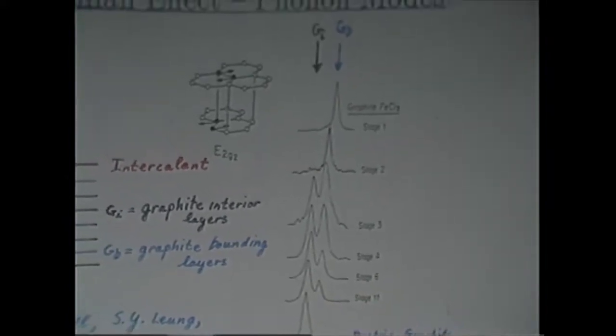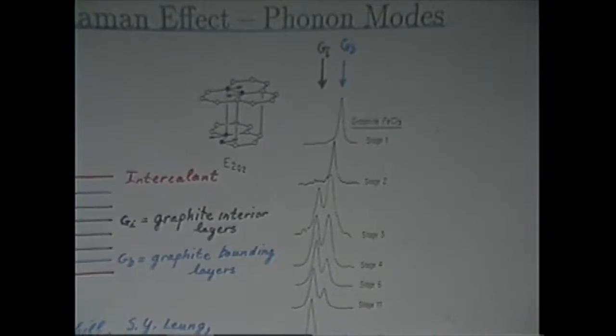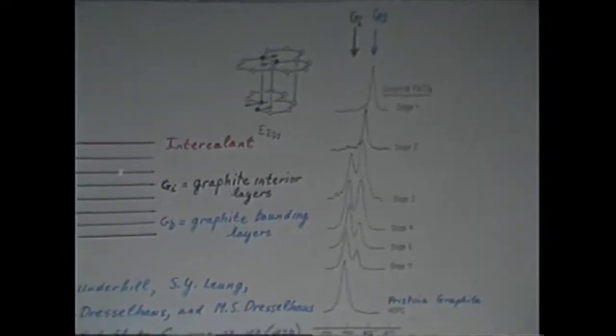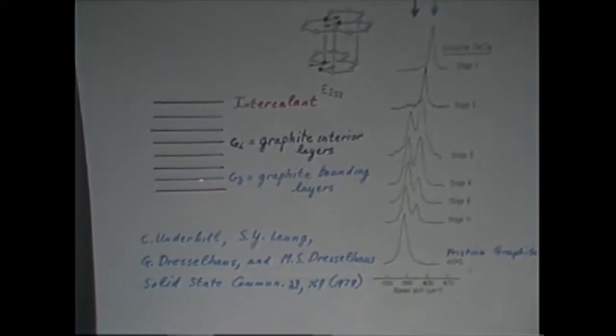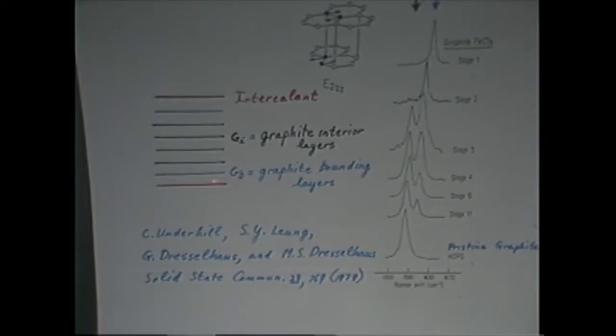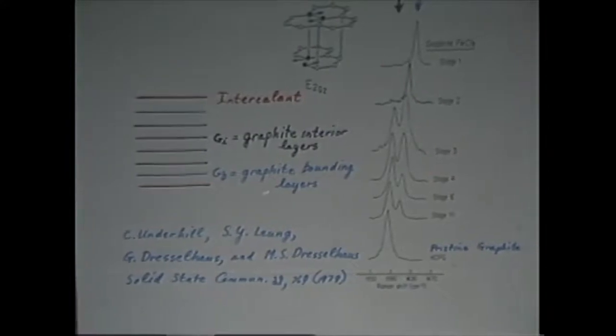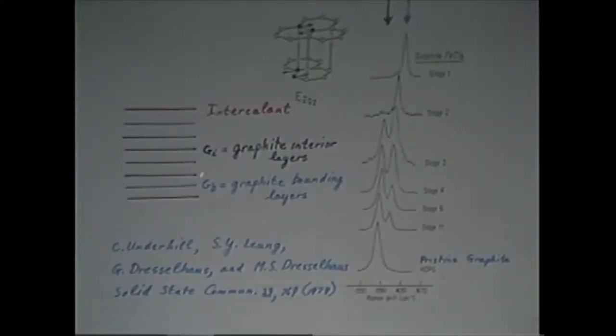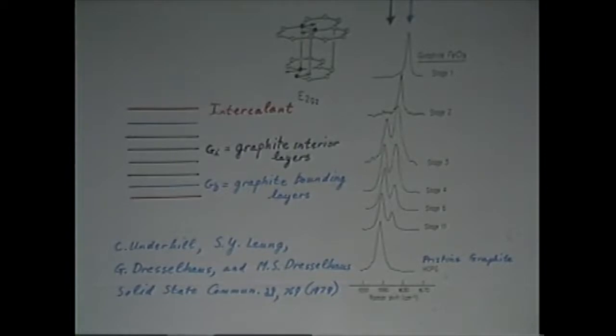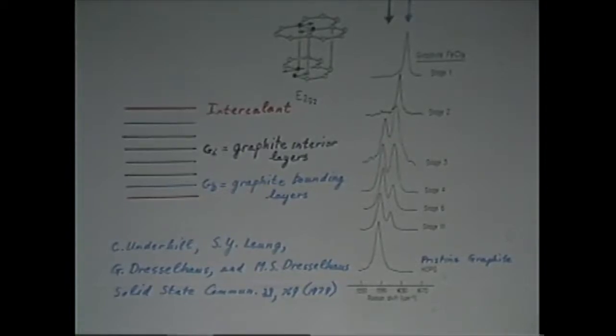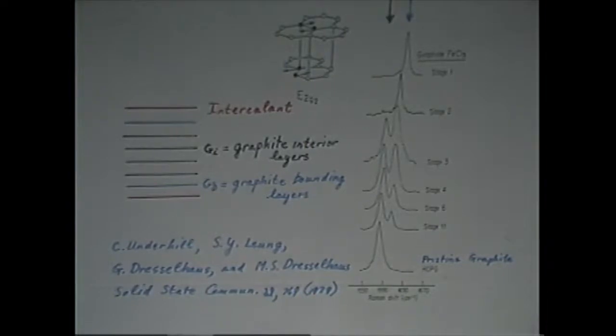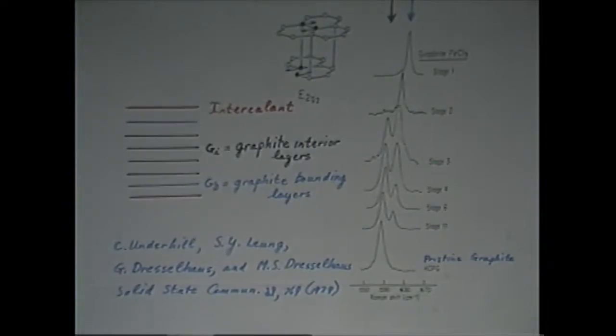Well, we came up with an explanation for this pretty soon, and the explanation is we had a bunch of graphite layers that were very strongly screened from the intercalant layer by a graphite bounding layer. And when you get to stage 2, all the graphite layers are graphite bounding layers. There are no graphite interior layers that are like the graphite. The layers that are just like the graphite give a resonance at the same frequency that the graphite does. But the ones on the bounding layer have a lot more charge, and they will give an upshifted mode. So that whole story made sense, even though the effects were minuscule.